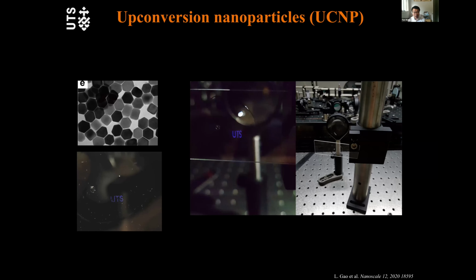An upconversion nanoparticle is basically just a nanocrystal. You can see from this SEM image there are lots of nanoparticles, about 50 nanometers in size. The amazing thing about this particle is that if you shine near infrared light on the material, it will emit bright visible light. If you mix these nanoparticles inside some thin film, put it on a glass slide and just scan your mirror, you will see really bright emission, and you can scan in real time for 2D video display.